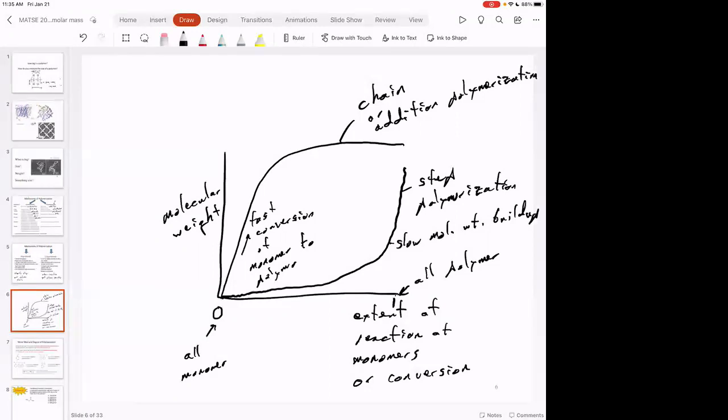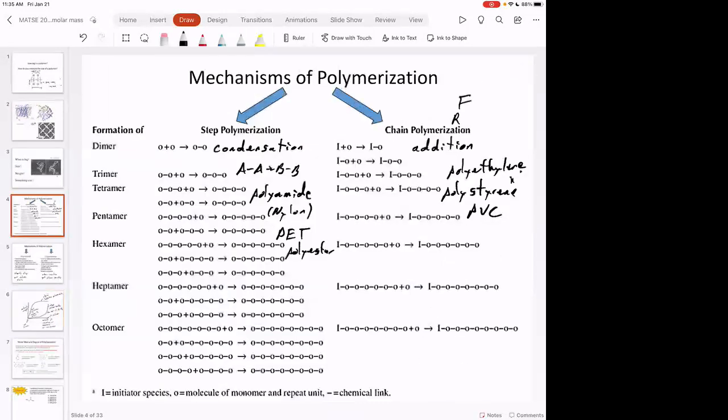Yes. Why is step polymerization used, although it is slower than chain polymerization? Yeah, this is a really good question. Why do you need two different polymerization mechanisms? Why would you use the slow one? The answer is that you can't make PET, you can't make nylons, you can't make a lot of different polymers with only chain polymerization. You can only make them with step growth polymerization. These different polymers have different properties, and so you need both. That's a good question.